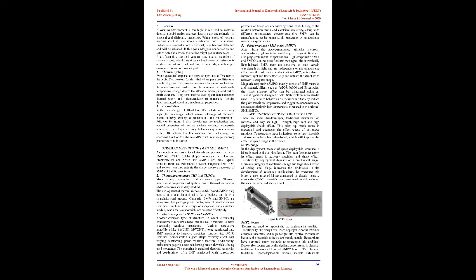3. UV radiation. With a wavelength of 10 to 400 nanometers, UV radiation has very high photon energy, which causes cleavage of chemical bonds, thereby leading to microcracks and embrittlement, followed by aging. It also deteriorates the mechanical and optical properties of thermal surface coatings, composite adhesives, etc. Shape memory behavior experiments along with FTIR indicate that UV radiation does not change the chemical bonds of the above SMPs, and their shape memory properties remain stable.